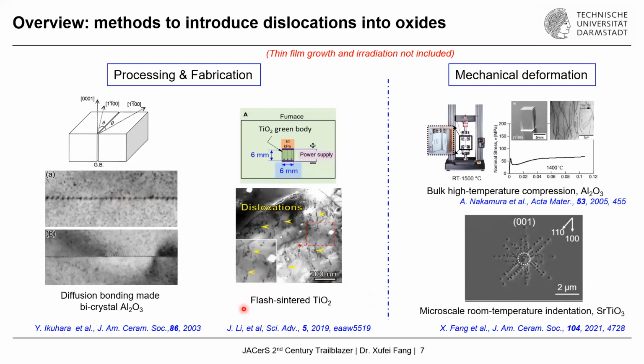Another example would be the so-called flash sintering technique. As you can see, the green body here is subjected to an electric field and also electric current flow. Due to the highly non-equilibrium process, dislocations can be generated or maintained in the bulk. But the challenge of using this technique is that besides dislocations, we can also see a lot of other types of defects, for example, voids, pores, and grain boundaries, making the scenario rather complicated to solely study the dislocation-based mechanical and functional properties.